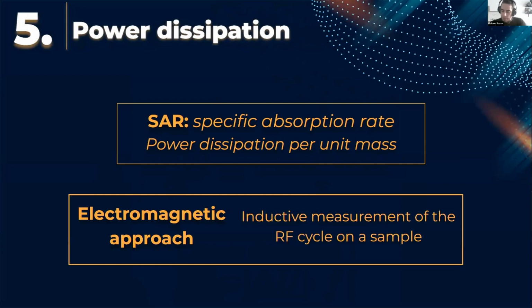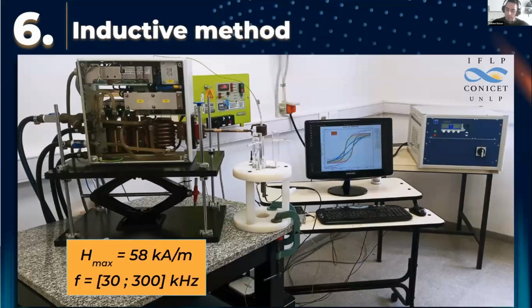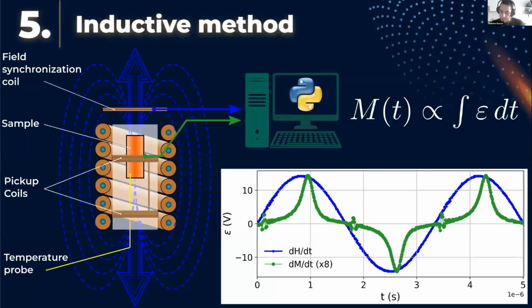The SAR, specific absorption rate, of the set of magnetic nanoparticles depends not only on the field parameters, but also on the supporting medium and the spatial distribution of the nanoparticles, which influences dipolar interactions between them. We use the electromagnetic approach in order to obtain the radio frequency cycles of magnetic nanoparticles. This is a picture of our setup, and this recently developed technique is based on the inductive measurement of the electromotive force generated in a sensor coil pair by the time derivative of the sample's magnetization.